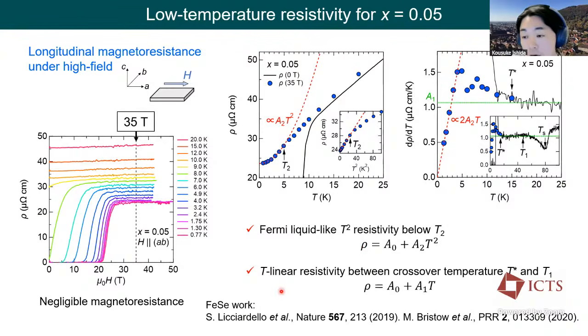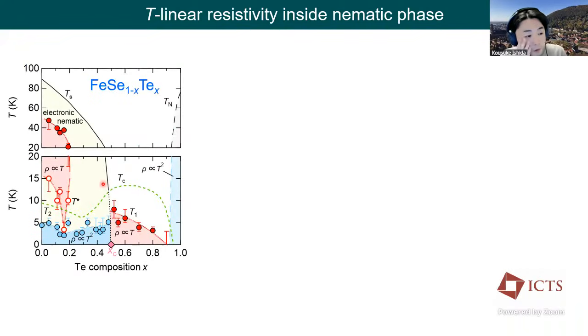These behaviors are almost similar to the previous high field work on iron selenide. So the analysis applied here is, I believe, reasonable. And then we performed systematic measurements on a series of FeSe-Te to see how this T-square and T-linear resistivity regime changes with increasing x. And this is the obtained phase diagram, a summary of these measurements. The blue region is a Fermi liquid-like T-square resistivity regime, and the red one is the T-linear resistivity regime. And as you can see, the onset of these two regimes is completely hidden below superconductivity. So destroying the superconductivity by high field is required for a proper discussion.